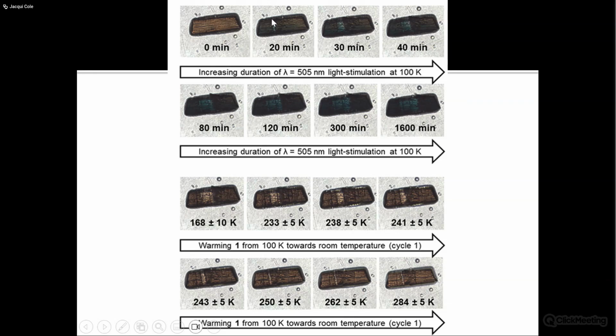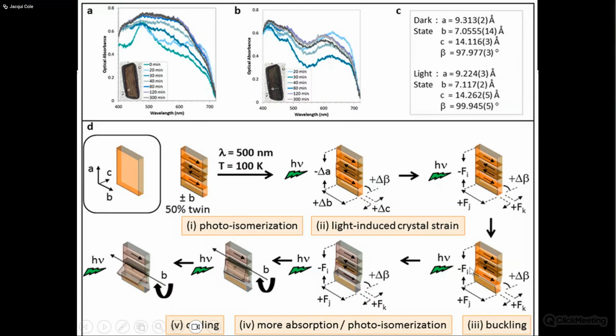So you see the cut and then the light induced, it's starting to peel up, and then it's getting darker and darker, and it's really peeled up here. And then you put the heat on it and warm it up, and then it goes back to its original configuration. And it's repeatable. So we even put in some optical absorption microscopy, and you basically have a 2-dimensional grid in terms of the optical absorption spectroscopy. So what you can do is actually find the pixels on the crystal for each different optical absorption part, if that makes some sense.